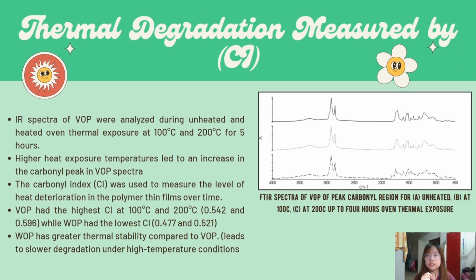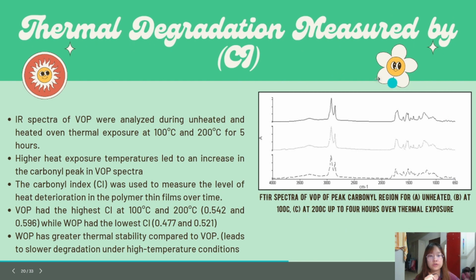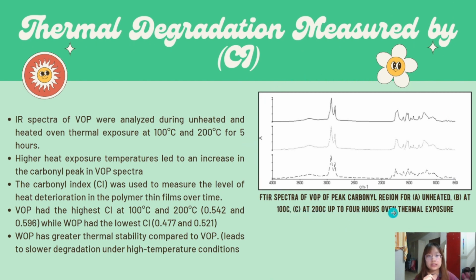The next one is thermal degradation measured by CI. This is the FTIR spectra of virgin oil polymer during unheated and heated oven thermal exposure at 100 degrees Celsius and 200 degrees Celsius for 5 hours. Generally, the carbonyl index was used to measure the level of heat deterioration in the polymer thin film over time. The VOP has the highest CI and the WOP has the lowest. Therefore, WOP has higher thermal stability compared to VOP, which leads to slower degradation under high temperature conditions.